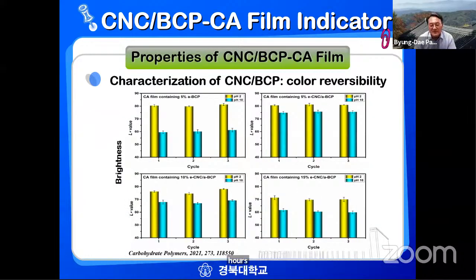And also we check the brightness of these films at the different pH 2 and pH 10. The 5% control and the 5%, 10%, 15% composite materials, there's not much change. The color changes are still reversible, and so are the brightness and the delta E value.